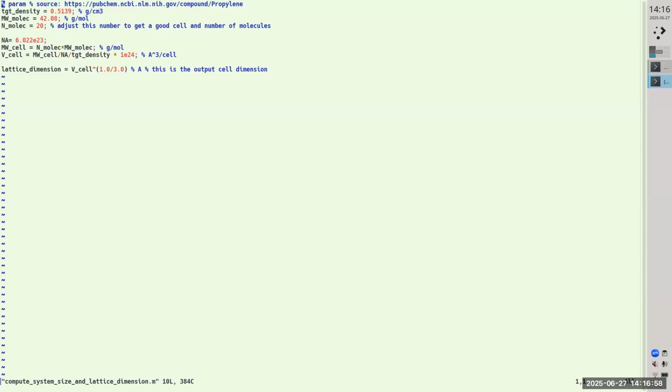The number of atoms is of the order of a few hundreds. So that's the guiding principle when it comes to setting up this particular calculation, which I think Bharata has probably already gone through with all of you. I said about the size 1.13 to 1.14 lattice. I see. Okay. I think pushing towards 1 nanometer is a little bit too small. But if you're hungry for computational resources, you can probably push it a little bit.